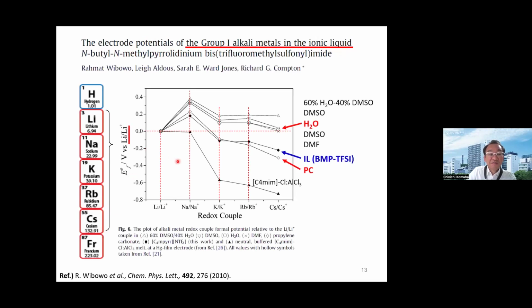If all potentials are referred to lithium as positive E0, then lithium is here. Depending on solvent and solution conditions, the E0 can change. In the case of sodium, the E0 is higher than lithium. But in propylene carbonate, the potassium and rubidium deposition potential is lower than lithium.